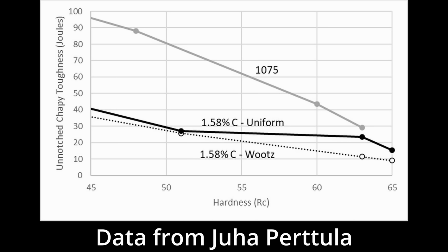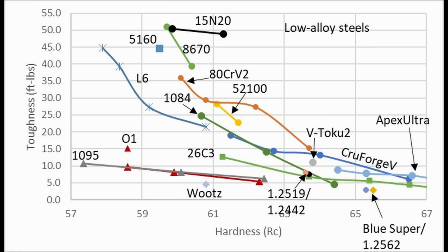But he also did another interesting study where he treated the Wootz to have a uniform carbide structure versus the banded Wootz-like structure. And with the uniform carbide distribution, the toughness was higher because he didn't have carbide bands anymore. So the Wootz had relatively poor toughness because of the high inclusion content, because of the high carbon content, and because of the carbide banding. So Wootz is not the best choice for toughness.